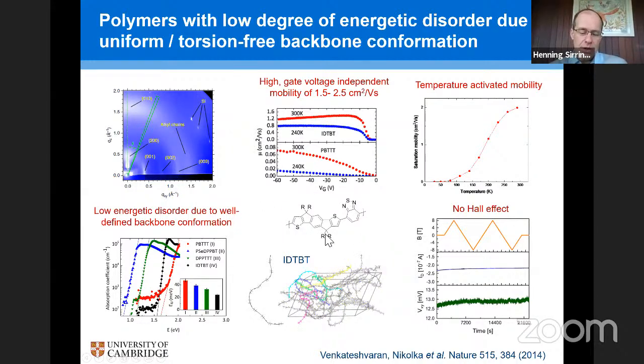And in the solid state, although the chains are not single crystalline, they are relatively poorly ordered in terms of their direction and orientation. But the local conformation of the backbone, if you look at this particular chain picked out of this ensemble, and you follow the molecular orientation along this chain, you can see that it's pretty much planar. There are no torsional defects. If there were torsional defects, you would see that in this projection. There's essentially a planar graphene-like nanoribbon that meanders gently as you go along the polymer chain. And because of this lack of torsional defects, the energetic disorder in these polymeric systems is now quite low.